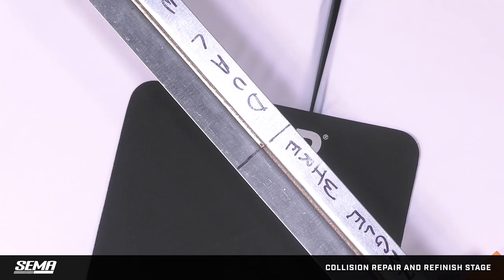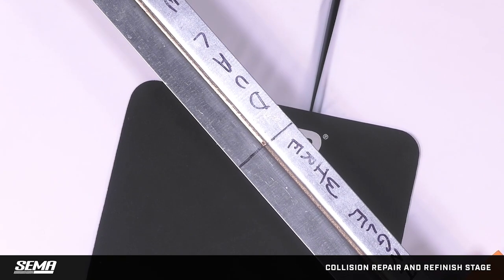A little wider profile. So that was one of the more challenging things for me to wrap my head around. With traditional MIG-MAG welding, I'm building a weld profile and I'm dwelling in that area longer with my torch, versus this process, you're essentially laying down the diameter of the electrode wire at a particular point, and moving on. You're not dumping more wire in one spot. No, we're not building it up. Right. Your travel speed is very close to the speed that you're pushing wire out.